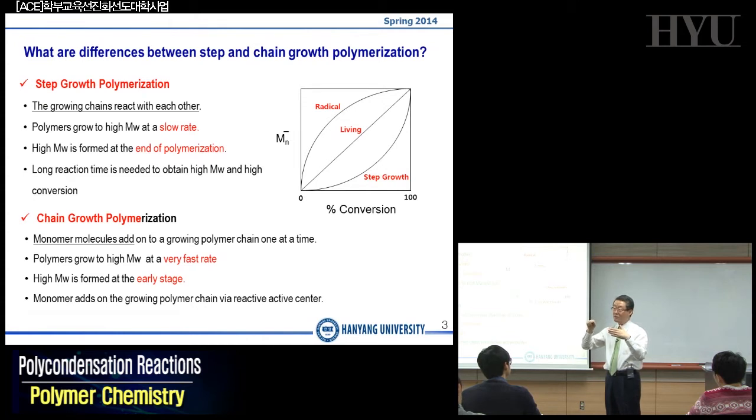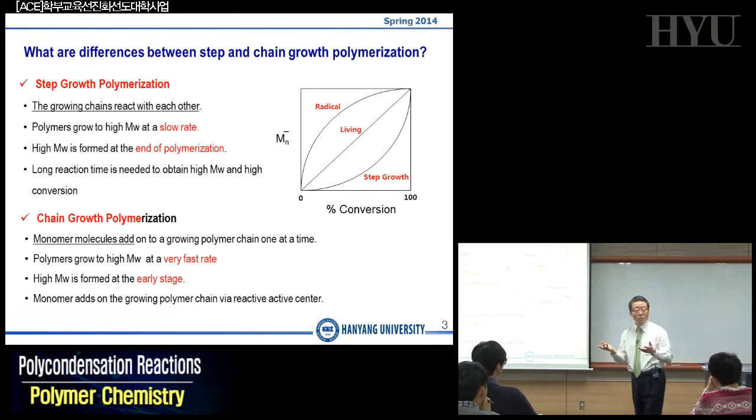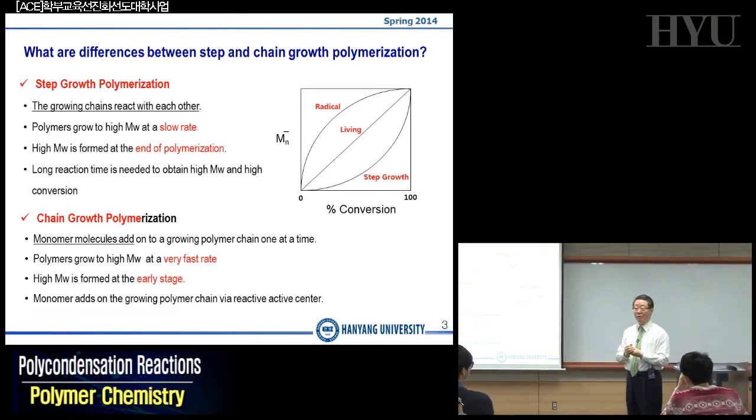Okay, anionic species still alive in the reaction vessel, and later, if you add some more monomer, then it will be added as well. So there is no loss unless you have water vapor or water in your reaction system. Water very much causes the termination reactions, but except for the presence of water, you will be able to make the living polymerization reactions, step by step.